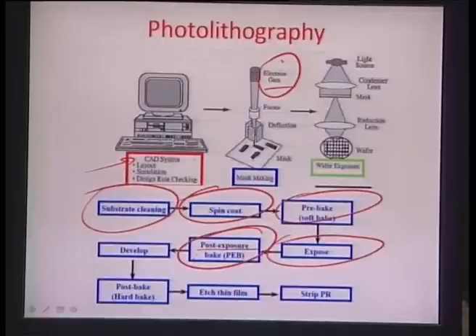So this cross bonding action is sometimes catalyzed by heat. So there is a tendency of heating the exposed wafer in another step here so that the resist can get fully catalyzed. If you can give sufficient time, instead of heating the same effect can be achieved just with time, but heating is normally done to quicken the processing of the resist. You then develop the particular resist. So in case of negative tone, the areas which are unexposed go away, and in case of positive tone, the areas which are exposed to the light and debonded in the process go away. And so in either case there is the formation of the design of the mask on the top, or the transfer of the design of the mask on the top of the resist.